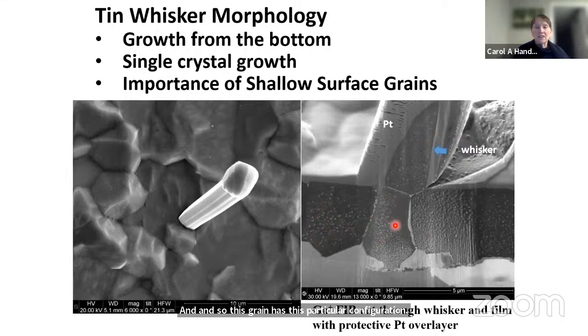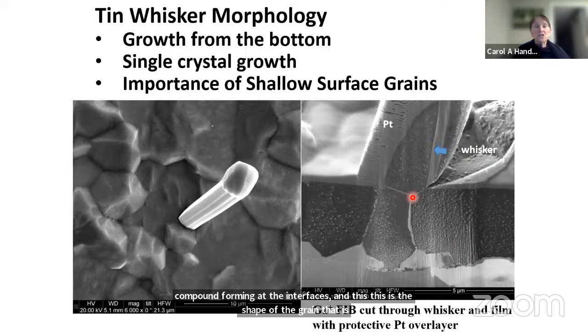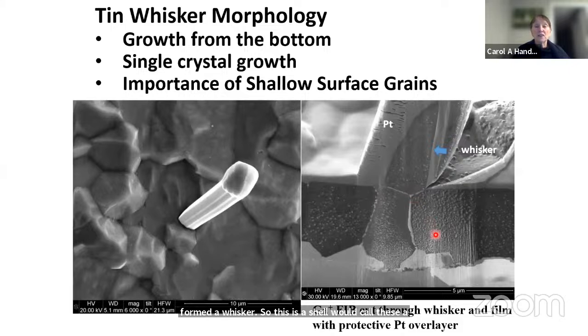The spots here are actually an artifact of the FIBbing, and it's some more general intermetallic. You can see the intermetallic compound forming at the interfaces, and this is the shape of the grain that has formed a whisker. We call these a shallow grain. Most of the grains in the film are columnar grains. The shallow grain has a particular driving force for migration, for atoms to migrate there. So this was the cut through this particular grain, and this was the FIB cross section.